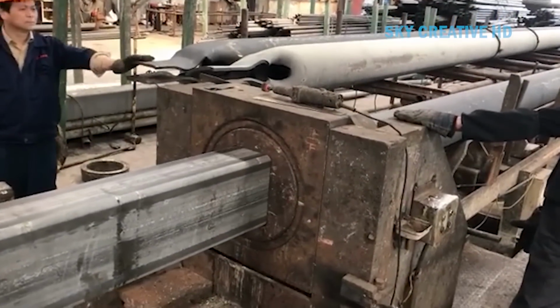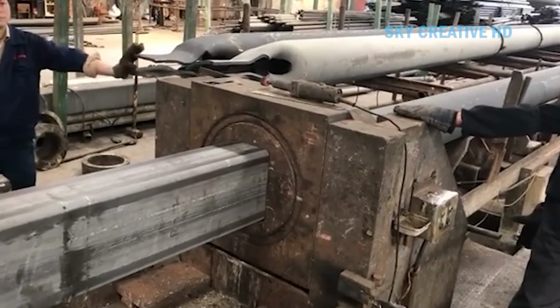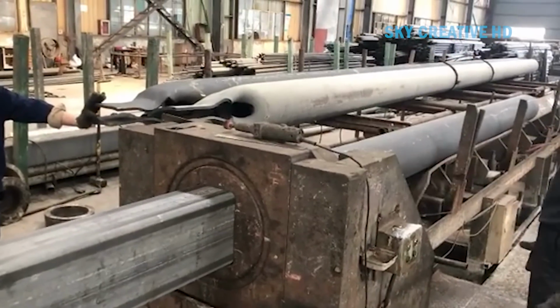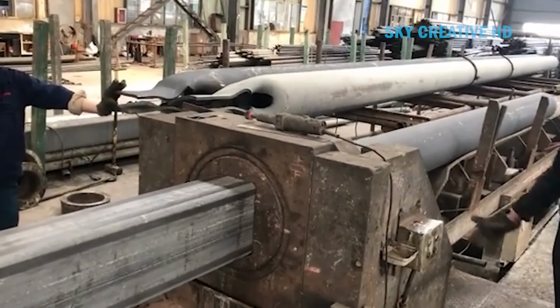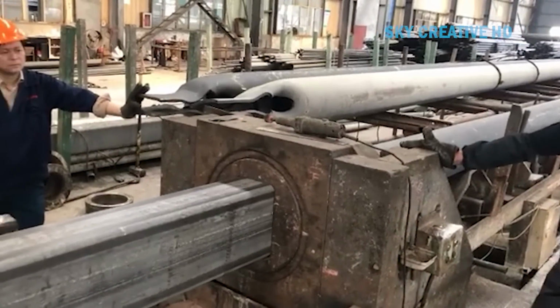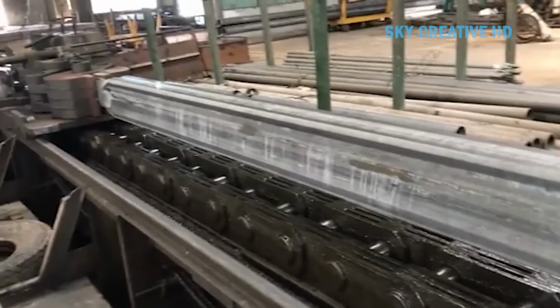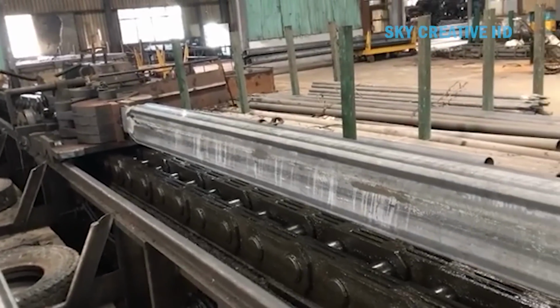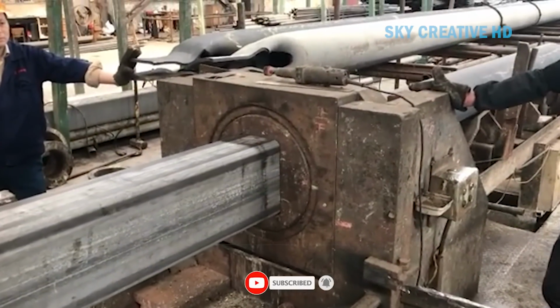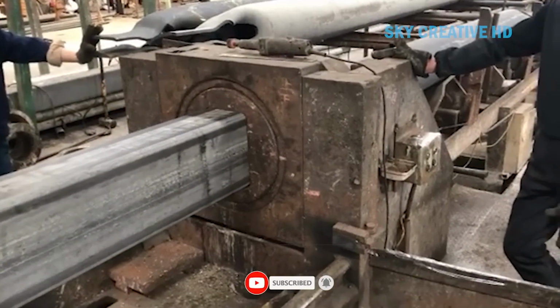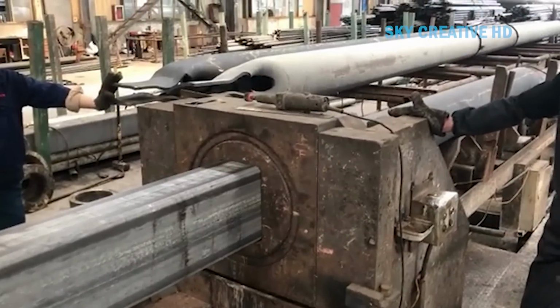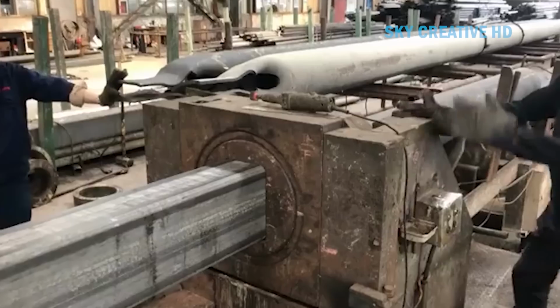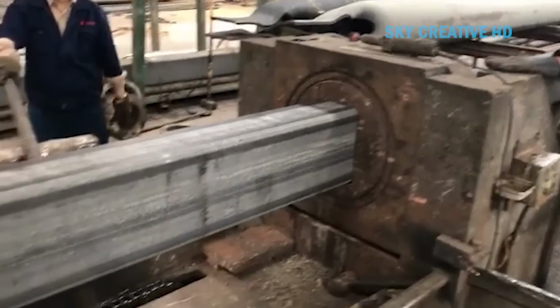Cold drawing is the most important step in forming square pipes. The round pipe is drawn through a die to form a square or rectangular shape. This process is carried out at room temperature, plastically deforming the tube and changing its shape. Cold drawing is usually carried out in several stages, each stage using a smaller die. This helps control the deformation and avoid cracking of the tube. The number of drawing stages depends on the required deformation and the wall thickness of the tube.